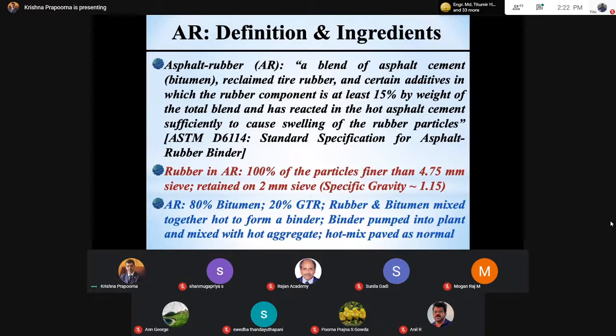Now, if you talk about the open graded asphalt rubber, gap graded being 6 to 8%, open graded, which is much more porous in nature, the binder content will vary anywhere between 8.5 and 10%. You see, much richer. It has more space to accommodate more rubber, so go ahead, use it. We have been very successful in blending both in India, also in our own laboratory facilities, and we have also tested on actual field sections, which I'm going to share with you. So this is the prologue of what we will discuss today.